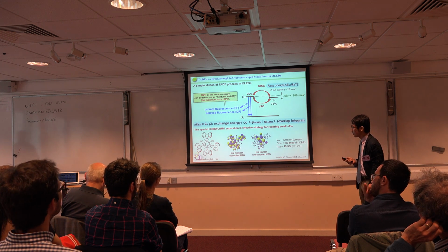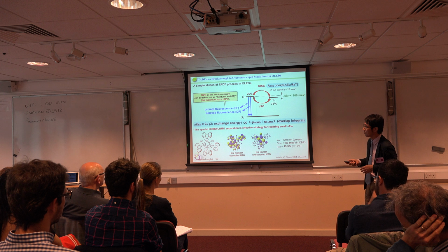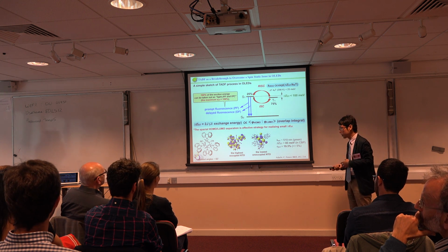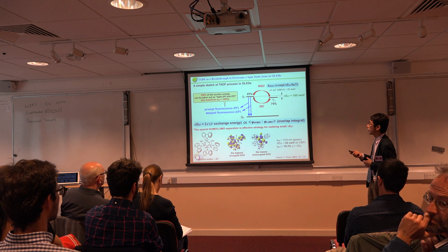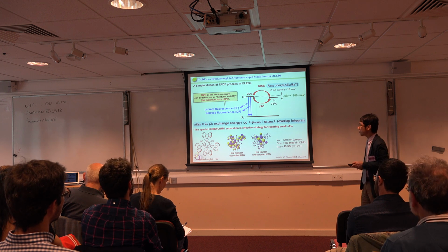So in 2012, Professor Adachi at Kyushu demonstrated that highly twisted donor-acceptor structure molecules can allow for an efficient RISC process to give delayed fluorescence by a thermal process.